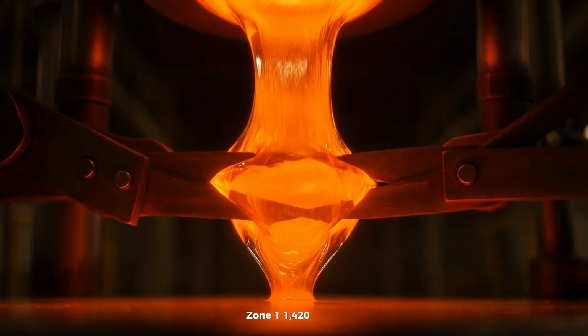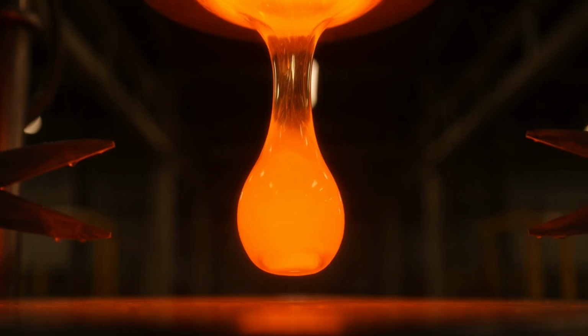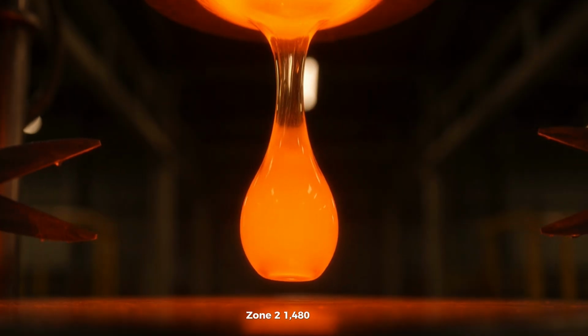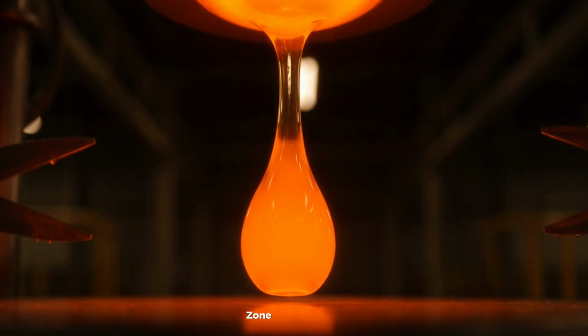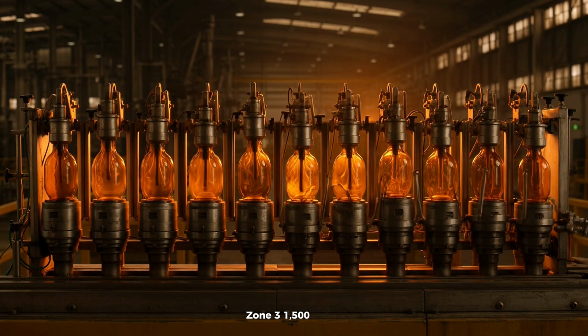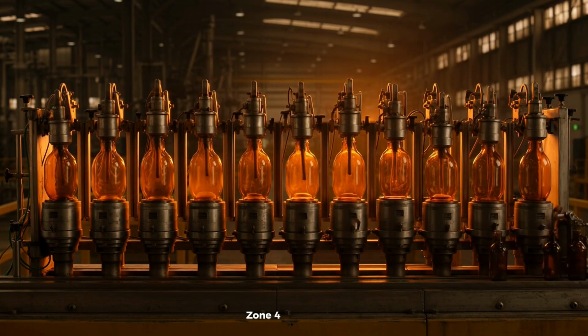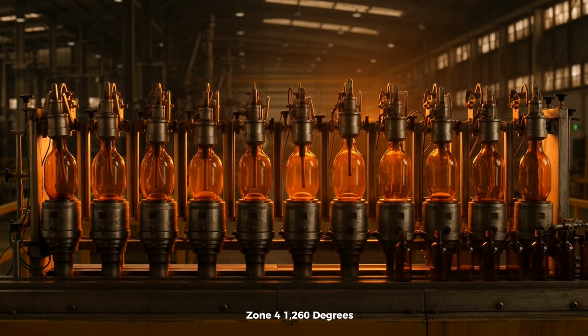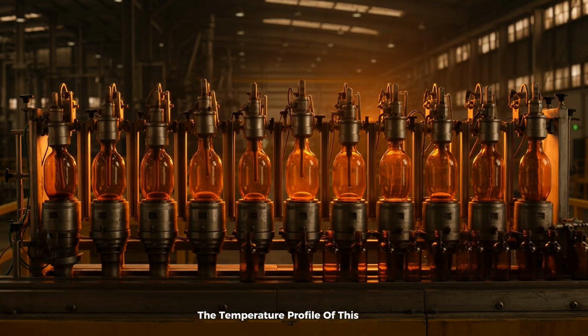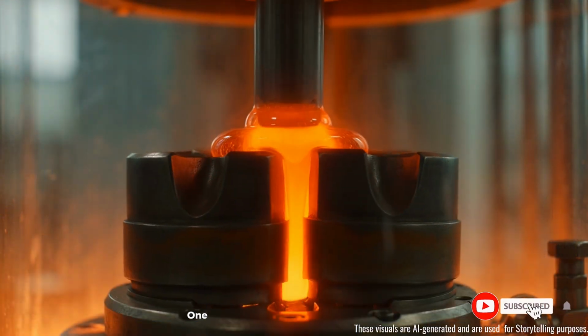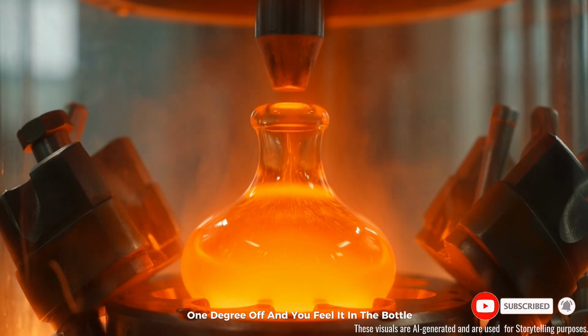Zone 1, 1,420 degrees. Zone 2, 1,480 degrees. Zone 3, 1,500 degrees. Zone 4, 1,260 degrees. The temperature profile of this furnace is the most critical variable in the entire factory. 1 degree off, and you feel it in the bottle.